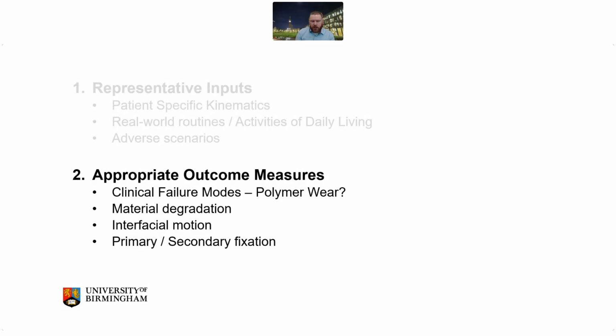And also in the switch to these antioxidant and harder polymers, where the wear rate has been driven down, there's work that's starting to come out of the States, which hasn't quite been published yet, but I've seen it presented at a conference, where you essentially have non-detectable wear on these new polymers, but you're still seeing osteolytic failure in tissue analysis. And the academics over there describe it as a cloud of almost undetectable polymer debris existing in the joint space. So the wear rate has fallen down, but we're still seeing that kind of osteolytic aseptic loosening driven failure mechanisms.